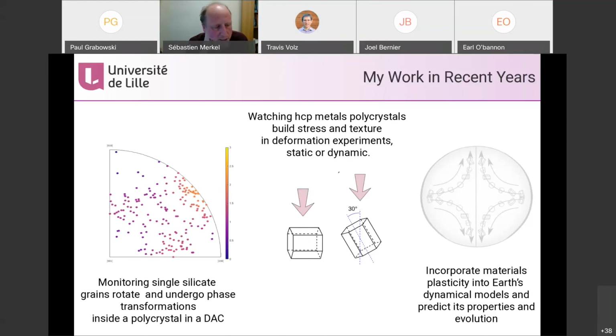With the new laser heating experiments, when we try to invert the grain positions, it seems very consistent. The strain tensors, I'm not sure. For these experiments with resistive heating, no, we don't get good positions.